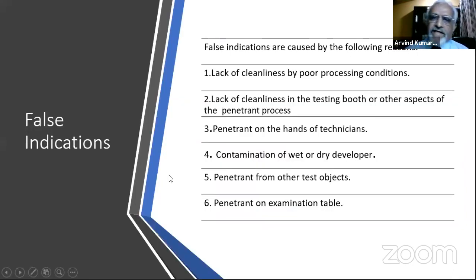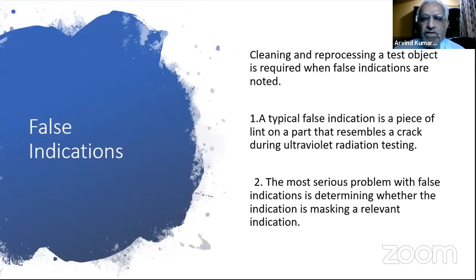The false indications can come because of various reasons. Some could be because the cleaning is not done properly. The cloth that you used is not lint free. It has some threads and all, which will leave penetrant and give an indication later on when you apply a developer. Or the technician's hands, he has put his thumb impressions here and there. There could be various reasons for having a false or irrelevant indication. One should know about it so that during interpretation it becomes easy to make out whether it is a real indication or a false indication.